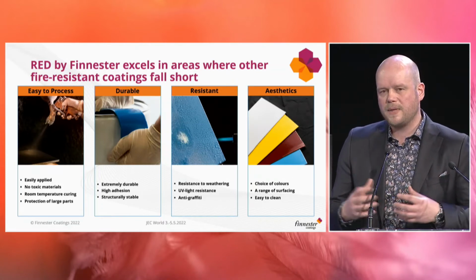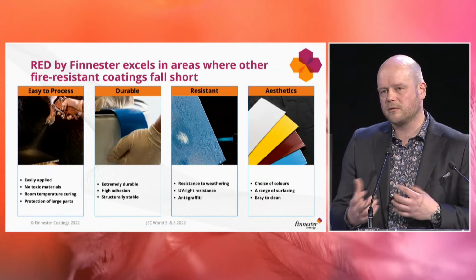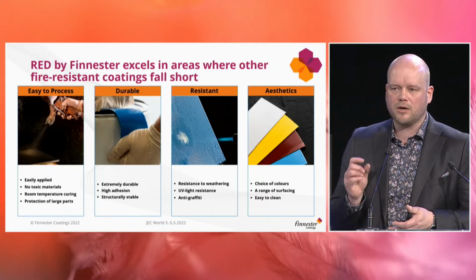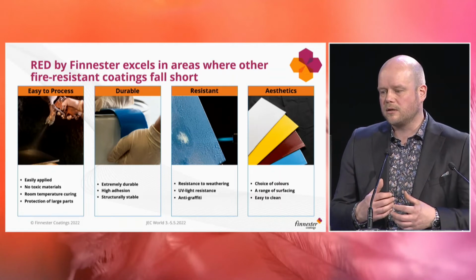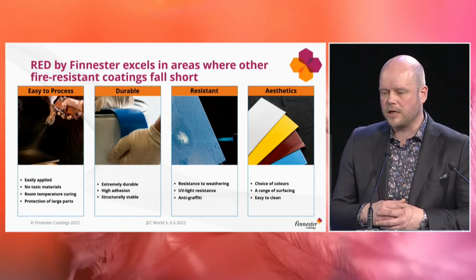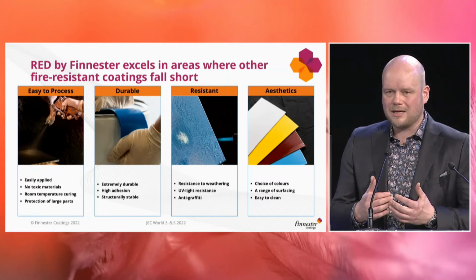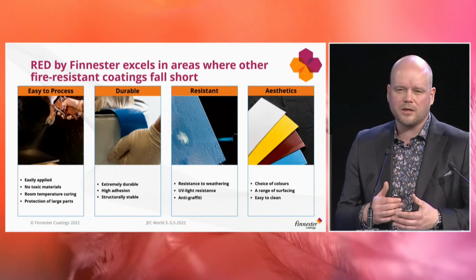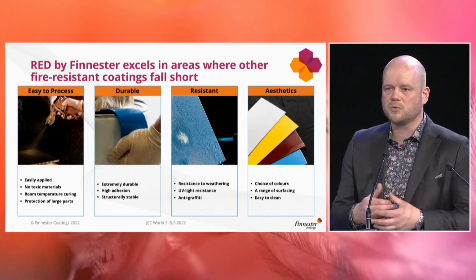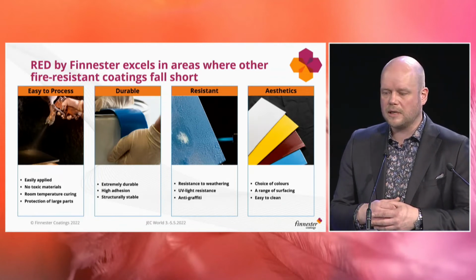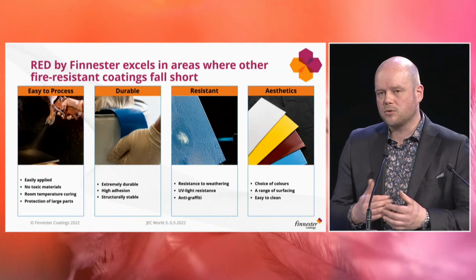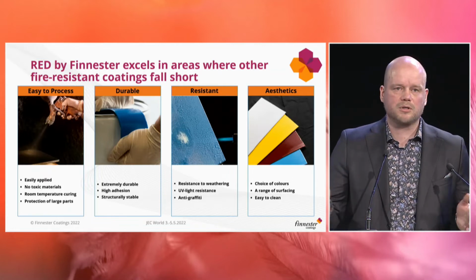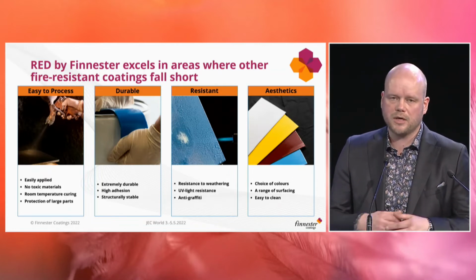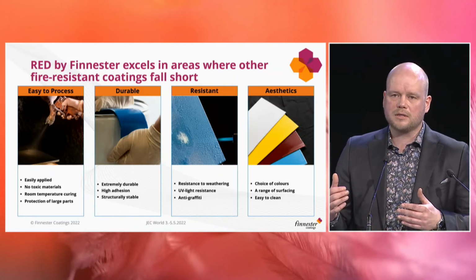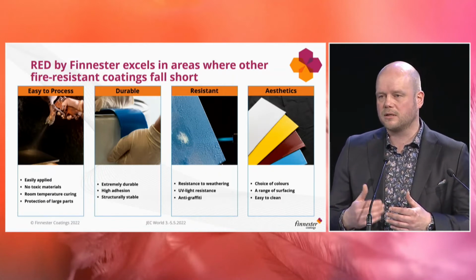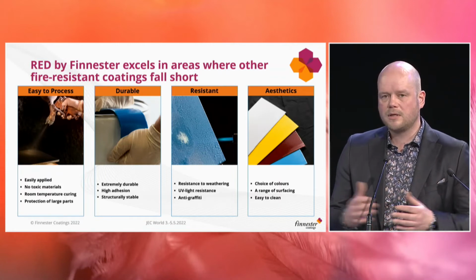No different in that. These are two-component systems, so you have a 10-hour pot life, very high solids, very low solvent content. You can easily spray for a whole day after mixing the batch. There are no toxic materials in there, no fire retardants in the products that would cause problems like antimony or halogens. These are room temperature curing systems, so you just paint big parts and leave them. You wait 2 weeks and it's ready to go, but it's a double curing system in the sense that in half an hour you have a tack-free, dust-free surface.